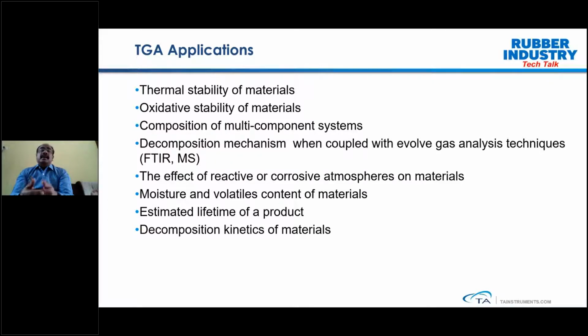And as I told you, with the TGA we have the option to change the atmosphere. Most often studies are performed in a nitrogen atmosphere, but sometimes you can also work in a reactive atmosphere, and then you can see how the material is going to decompose in a particular atmospheric condition. Apart from that, we have moisture and volatile content of the material, estimation of the lifetime of the product, and we can also understand the decomposition kinetics of the material.